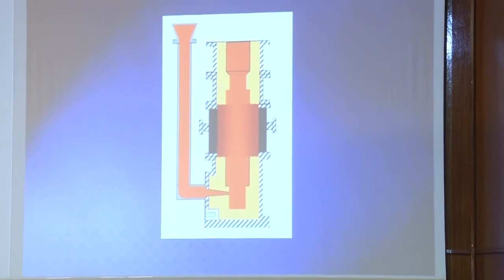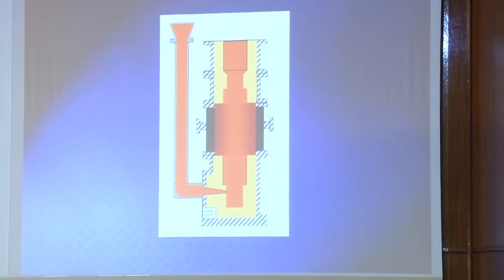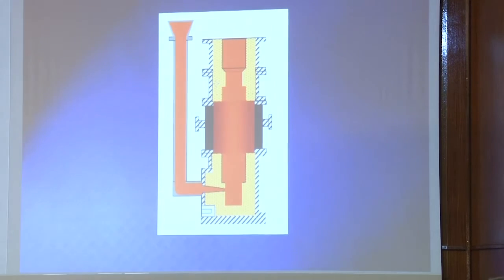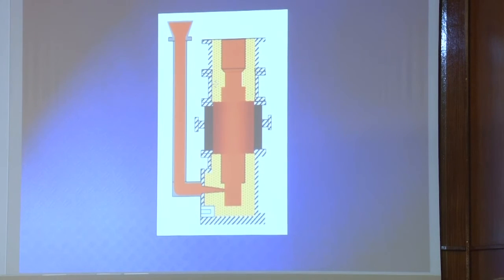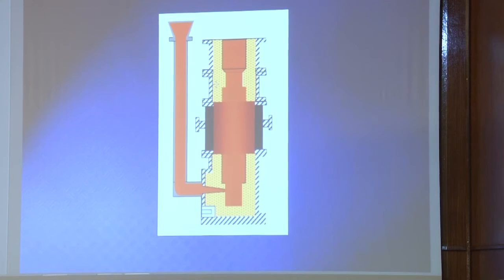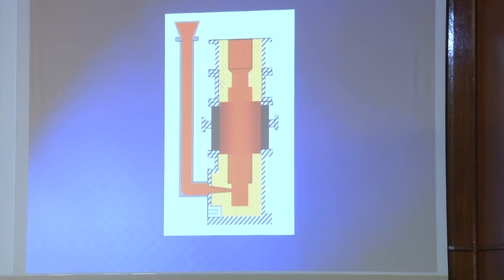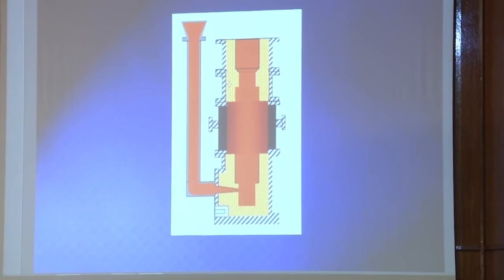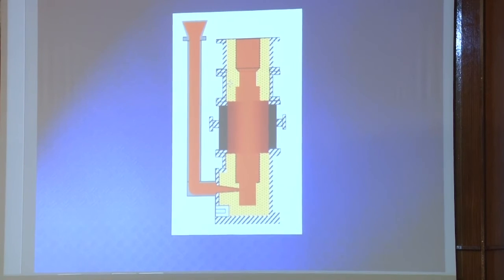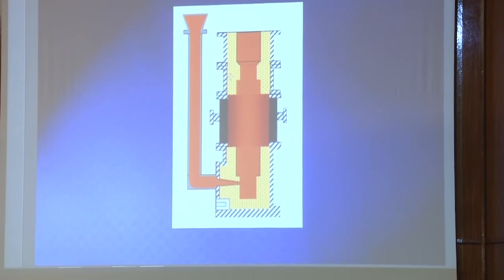This is the black one, a big cast iron mold die, or we call it the chill, because the main function is to increase the cooling rate of the iron and to promote the formation of carbides at the surface of the barrel. Meanwhile, the two necks, the lower and the upper one, are cast in green sand molds. Lower solidification rate will give you lower amounts of carbides and higher fracture toughness. We pour the metal from the top, and the metal will come and fill the mold.